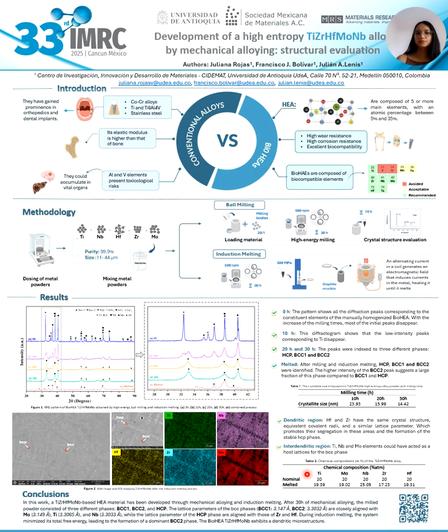In conclusion, in this work, a titanium, zirconium, molybdenum, hafnium, niobium based high entropy alloy material has been developed through mechanical alloying and induction melting. After 30 hours of mechanical alloying, the milled powder consisted of three different phases: BCC1, BCC2, and HCP. The lattice parameters of the BCC phases are closely aligned with molybdenum, titanium, and niobium, while the lattice parameter of the HCP phase is aligned with those of zirconium and hafnium.